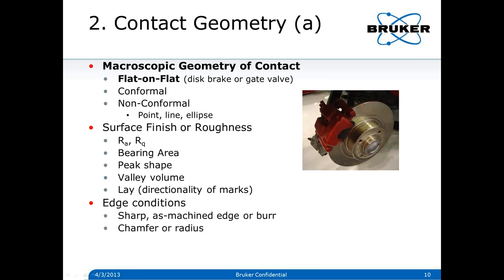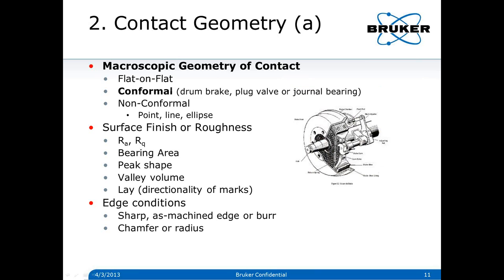When we get to contact geometry, we worry about macroscopic geometry and microscopic contact geometry. In macroscopic terms, I can characterize this as flat-on-flat — a typical disc brake or gate valve between seat and seat ring — or in a conformal contact we have two curved surfaces: a drum brake, plug valve, or journal bearing. In a drum brake, initially when you first put the brake pads on, they may not have exact conformality with the brake drum, so friction will be lower because you have less contact area.